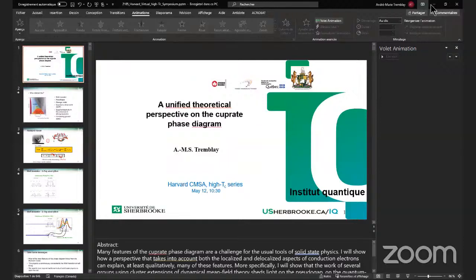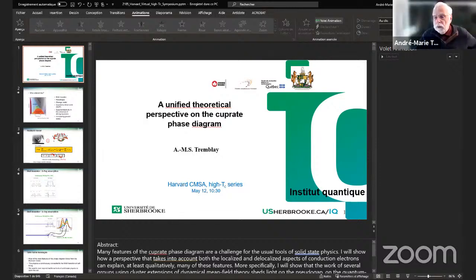You showed this very nice first order liquid-liquid or metal-metal phase transition. And there is a miscibility gap there, right? In some, yes. And I saw that TC often coincides with the critical point also around there. So do you expect this miscibility gap to be cured by superconductivity, or what happens around there? So what I plot here is the normal state results, except for these green points. But the point is that once you have superconductivity, this first order transition disappears in this one band model.